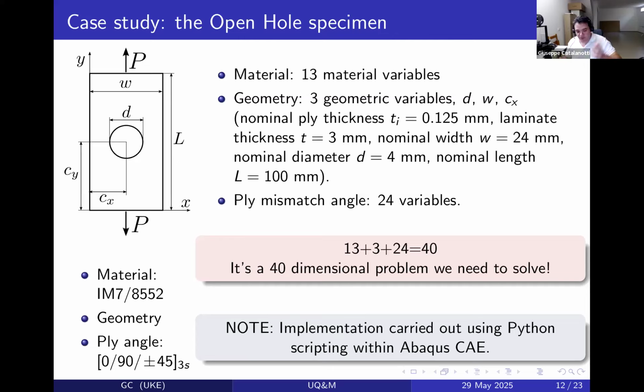I understand that. Of course, I'm not really aware of that, but I understand something of cracks. And you have some intrinsic and extrinsic mechanisms that can make crack propagation non-linear. You mentioned that there is a friction. We have, for example, the same things in composites when we take into account the propagation of a kink band. So it's like in compression, and you have this friction or this attraction in this case that acts along all the crack, and that originates this arc curve. I don't know how you model that, and that is perfectly fine.